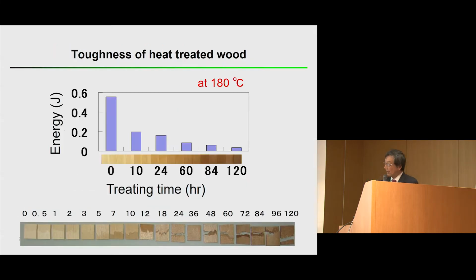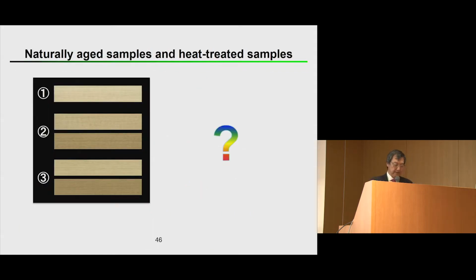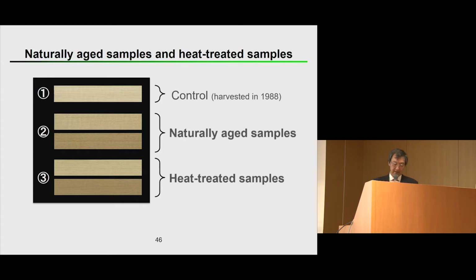And also you can see the color is getting darker and yellowish as the heating gets longer. So naturally aged samples and heat-treated samples together, we can see here the number one is the control harvested in 1988. Could you see which is which? Which one is the heated ones and aged samples in number 2 and number 3? The color of these two samples is very similar, and these two, another sample, are also quite similar. We can see the number 2 is the naturally aged sample, and number 3 is the heat-treated sample.